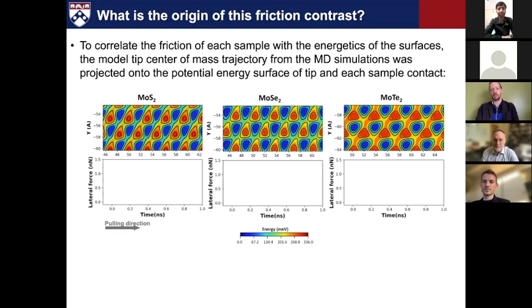Thank you, Professor. Welcome. How that would change friction would be a great question. If you get a phase transition, it ought to change the potential energy surface and potentially the mechanical behavior and the lattice constant a lot. So I think this would be an exciting thing to try to measure, especially for the 1T and 2H phase transitions. Accordingly, their local potential curve will also change, as per my understanding. Yep, agreed. And that can also be mimicked from SKPM and the potential mapping. Yep, agreed. Thank you. You're welcome.